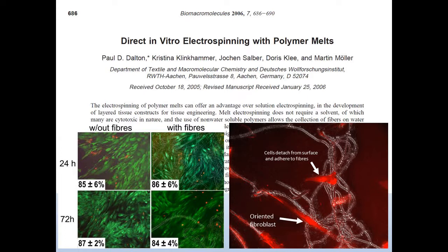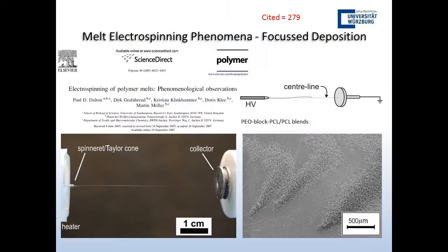We didn't have the facilities at DWI to really do this well, but we still tried to do it. And so we were getting Petri dishes and taking out of the cell culture fluid, running down the corridor, putting it into the chemical fume hoods and actually doing electrospinning. And that's where I found out if you have enough antibiotics in your media, particularly fibroblasts, you can push the boundaries of sterility. But yeah, we could actually see, and also the fiber deposition was really bad because fibers didn't want to electrospin onto Petri dishes. But this is something I think is interesting, and we'll probably pick up again in the years to come as we do more and more work on this topic.